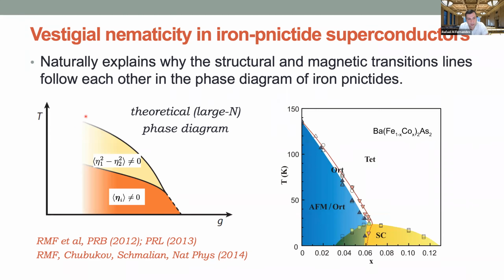If you look at this phase diagram, there was another phase I didn't mention, which is this red phase boundary here, that separates the tetragonal to orthorhombic. That's precisely this nematic phase. The tetragonal to orthorhombic is a 90-degree rotational symmetry breaking, and you see in the phase diagram how it's always very close to the magnetic phase. In this formalism, this comes naturally, as the nematic is a vestige of the antiferromagnetic phase.